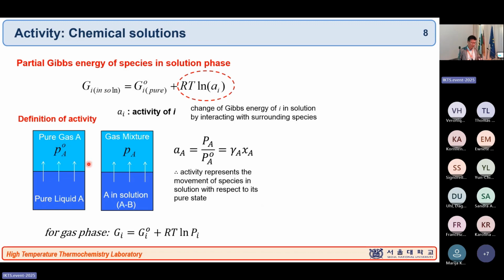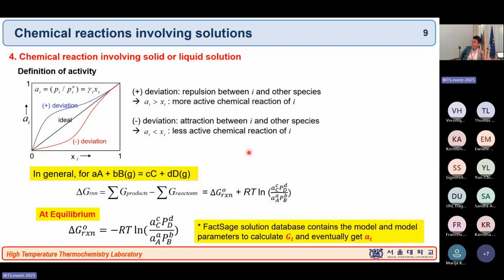And classically, we explain the activity by dictating this kind of partial pressure. This is ideal. And so activity is expressed typically by the activity coefficient and the mole fraction. Of course, it is very, very difficult to find the activity coefficient, and most of the time we have to do the experiment. In the FactSage, we have all the formulas which allow you to get the activity coefficient automatically, so you can do the equilibrium calculation. Depending on whether the species like each other or don't like each other, you can have different energy. And depending on that, you can have more attractive force, which means your activity coefficient is lower than your ideal condition. And if you have repulsive force, your activity becomes higher than your ideal condition. That's the presentation on that graph.